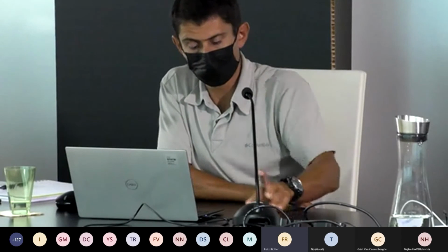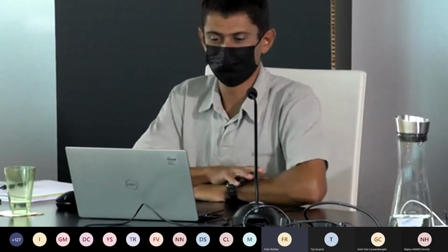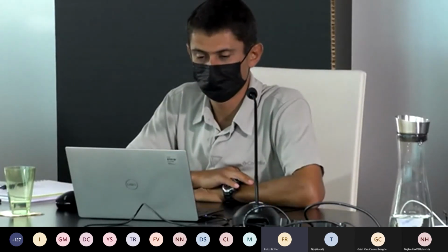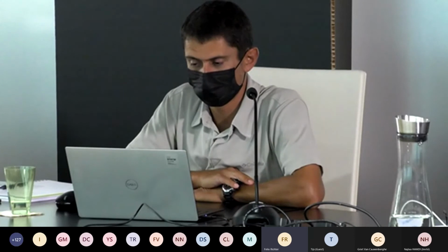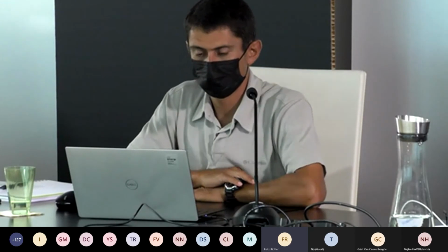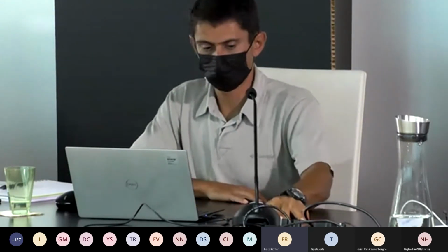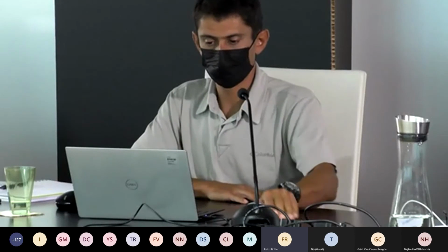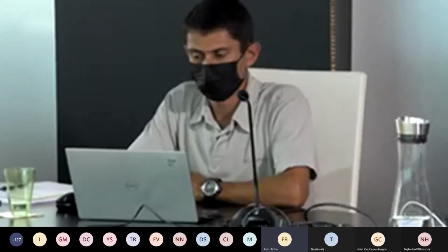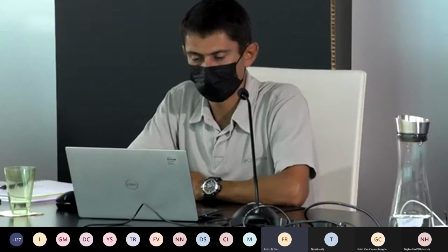Hello, yes, thank you for the question. So the grain size in particular depends strongly on the synthesis conditions of the pellet and temperatures and times for the synthesis. Typically, the grain boundaries are found to be the places where dendrites form, where lithium nucleation happens, and where dendrite initiation can occur. So it is, of course, very important to be able to tune this.